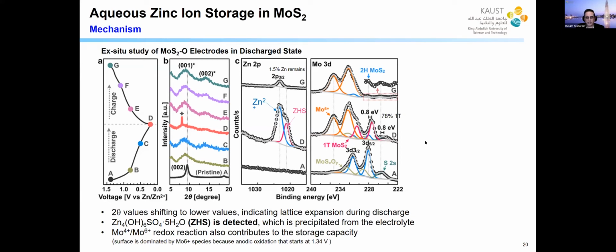In general, when we have these batteries, not only zinc intercalates, all aqueous batteries suffer from the fact that also protons from the electrolyte intercalate in the cathode. When that happens, you actually deplete the water near the electrode of protons, and it becomes hydroxyl rich. Therefore, the zinc reacts with hydroxide and forms the hydroxide and the sulfate, and it forms this phase. So this is actually on the cathode side, a byproduct of the proton intercalation. So we have now a way to estimate how much proton is intercalated here.